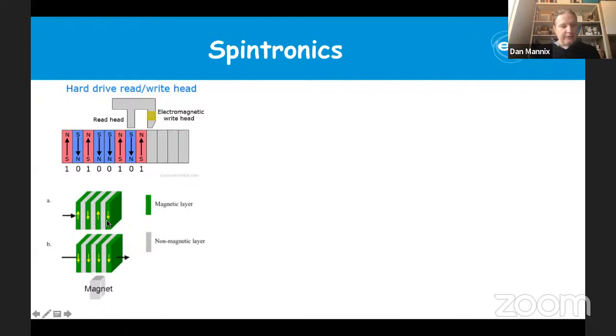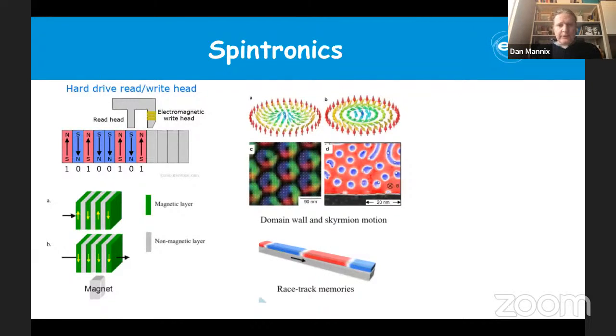So you can get a high resistive state or a low resistive state, and you can use that essentially to store this information. And that was really the start of Spintronics, really, the fact that you can have conductivity related to magnetic orientation. So there's a lot of research today that goes on in Spintronics, trying to look at how we can improve on these old technologies, whether we can actually get higher density storages by having much smaller domain size or much smaller magnets, packing them together.